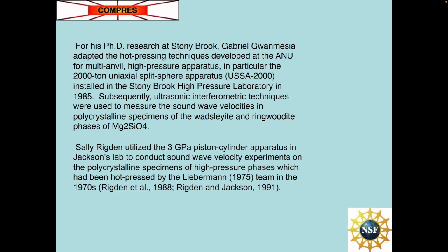Later, when Sally Rigdon worked in Jackson's laboratory, she used a piston cylinder apparatus to make high pressure measurements on some of the specimens that were hot pressed by our team at Stony Brook, and also had hot pressed at the ANU in the 70s. The next slide.